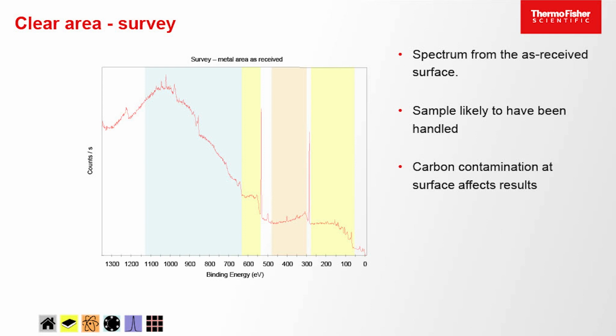Now, one of the classic ways to tell this, and this is proper advanced level XPS now, so it's a bit of a trade secret, keep it to yourselves. The shape of these funny steps in the spectrum is actually quite diagnostic in telling you where things are ordered on the surface. Now, as I say, I've been doing this for 20 years. I know this is a carbon peak, and I know this is an oxygen peak. But after this peak, I can see the shape of this background is curving down like this. And behind the oxygen peak, I can see it's curving up like this. And also, all these peaks here, rather than curving down, the background's curving up.